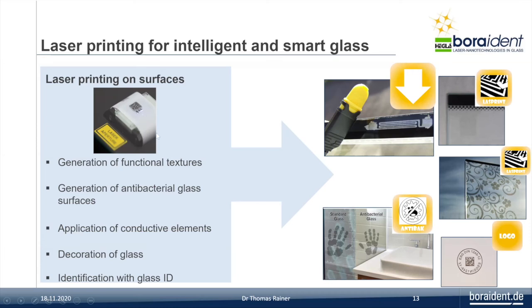And so if you have a conductive coating, then you can print alarm circuits. As well, if you have metallic films, you can decorate the coating. And at the final end, if you have silver ions, for example, then you can bring antibacterial function to the glass surface itself. These are examples of what we can do with the laser: remove coating, add a new material to the glass surface itself, and create new functions.